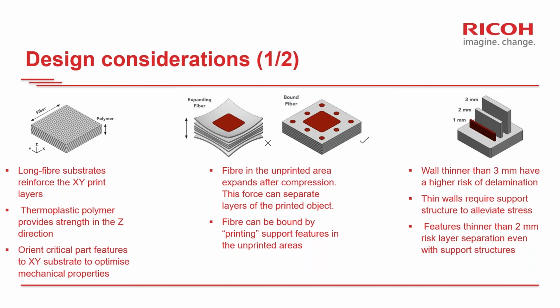So from a mechanical point of view, the parts have anisotropic properties, meaning that the mechanical properties in X and Y, where the fibers are randomly aligned, will be higher than in the Z-axis, where the strength will be mainly provided by the polymer matrix. So it is important when designing the part to orient critical features or areas that will be submitted to mechanical load accordingly.